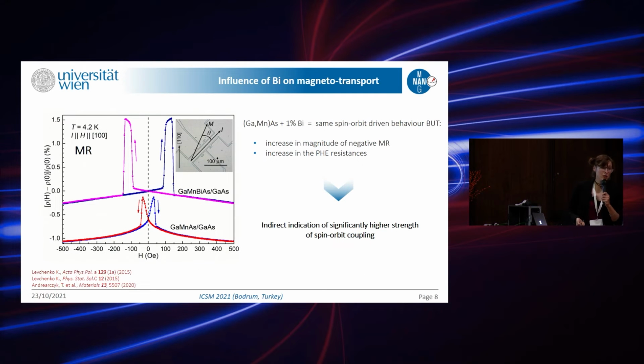And not only for the planar Hall effect, the same was observed for the magnetoresistance, as you may see here. But I would like to point your attention to the fact that both of those curves have basically the same phenomena driving them, the same shape, but the magnitude is increased, and coercive and anisotropic fields are increased, which means that when we add 1% of bismuth, we still have the same spin-orbit driven phenomena, but by adding a heavy material, we are enhancing them. So this is a qualitative characterization. We would like to quantify it.